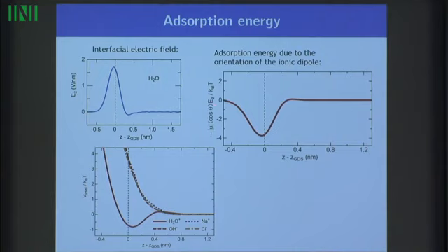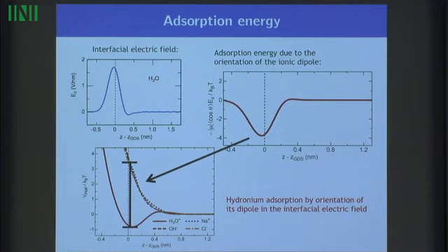And what you can see is exactly this type of energy profile. There's a 4 kT adsorption simply by orienting this dipole in the interfacial electric field. And that is roughly the same sort of 4 kT that you see here.